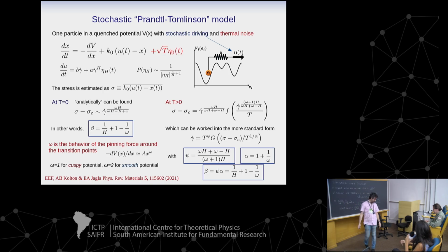I'm not saying it's not surprising, but after some time, I've learned to accept it and actually to push for it. I was skeptical about it because, yes, you have this 2D disordered system, amorphous solid whatsoever, but it seems that in statistical physics, long-range interactions are super powerful. They will erase whatever is in their way. And basically, as here, they end up putting all this information of the extended model and the rules, etc., in a single number, which is this noise. That depends on dimension. Another interesting thing is that it does not depend on the type of disorder potential, because the type of potential comes in separately from the noise.